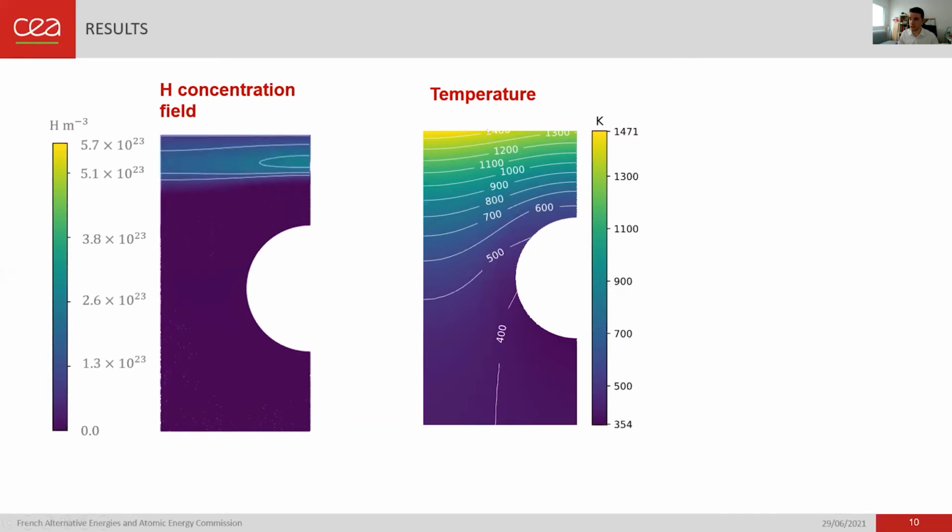So again, this is a plasma-facing surface where the heat flux is striking. So obviously we have a temperature gradient here. In a few words, what we observe is that we have a higher retention, being how much hydrogen is trapped in the solid, in the cold regions. And that's because it takes energy for the hydrogen to get out of a trap in the material.